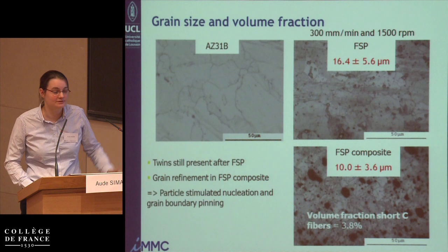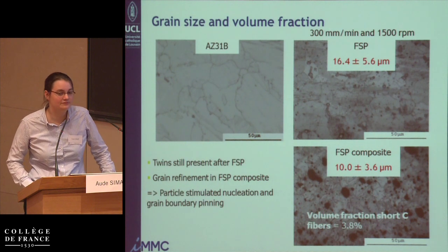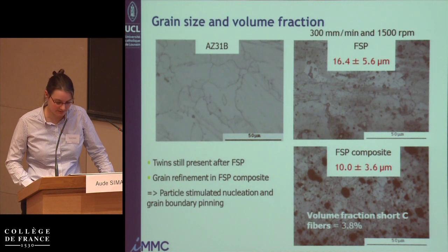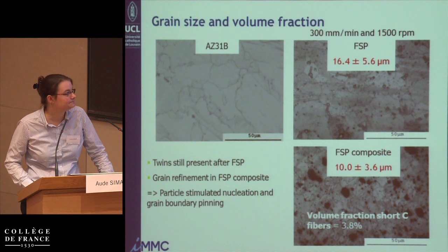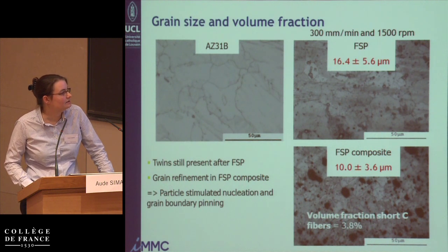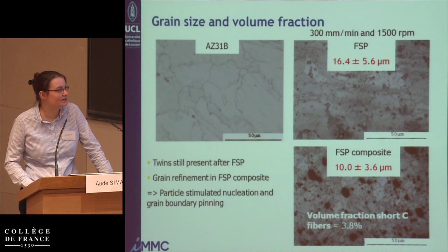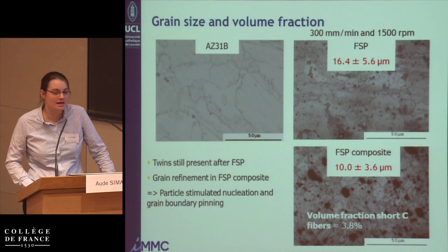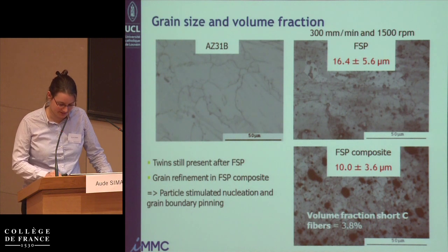But of course, you have defects here. We have defect-free material, and we have a grain refinement in the friction stir composite due to particle stimulated nucleation and grain boundary pinning, similarly to what I mentioned in the copper matrix material.